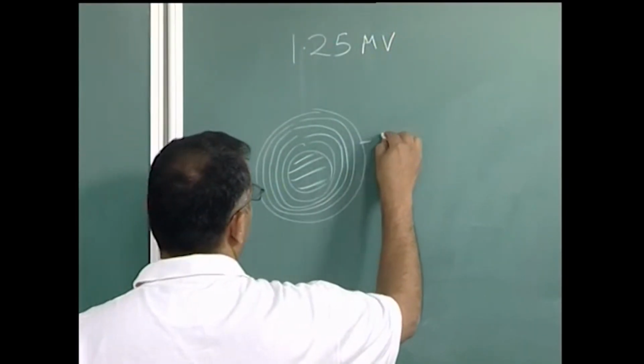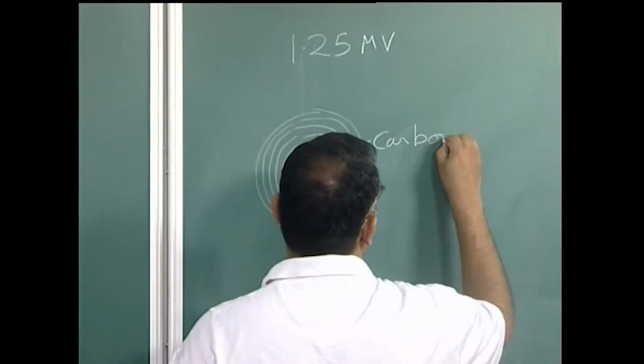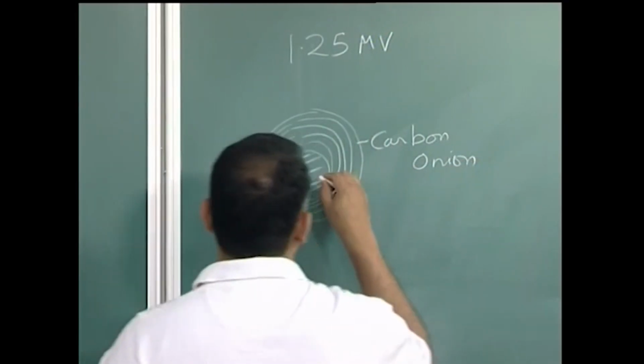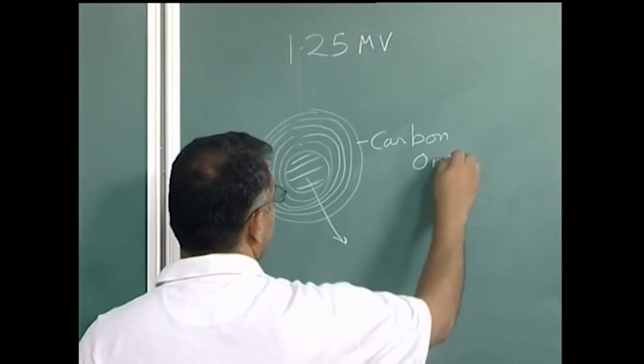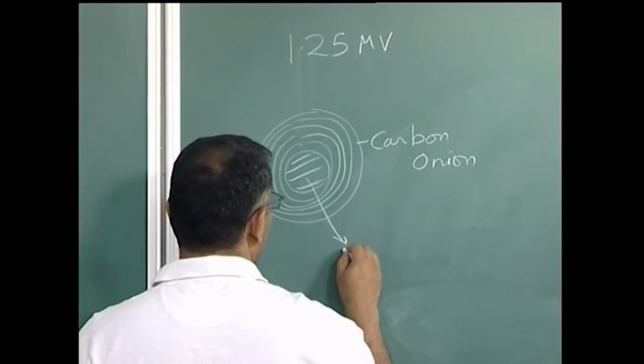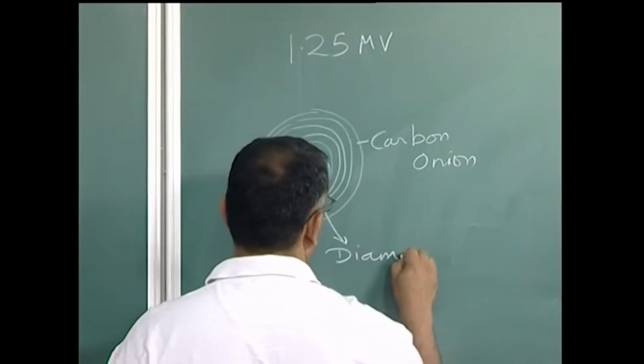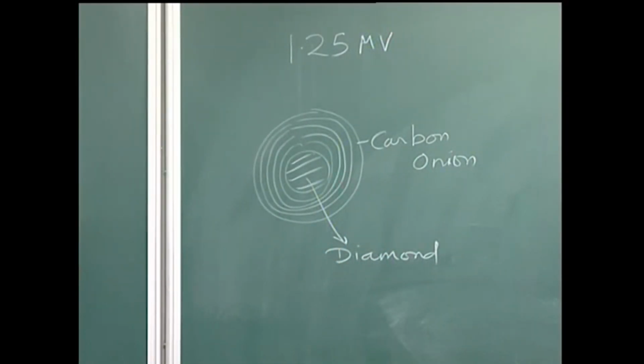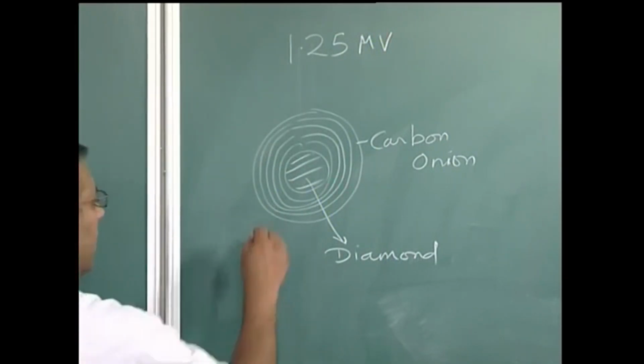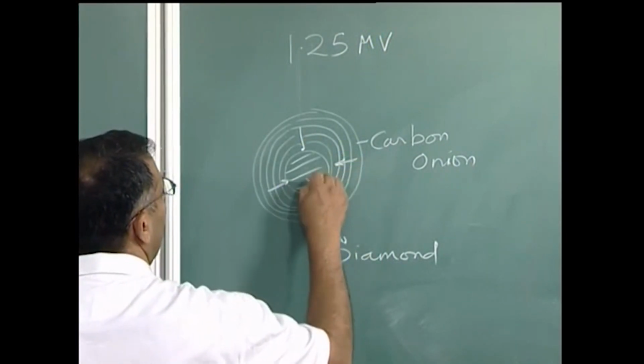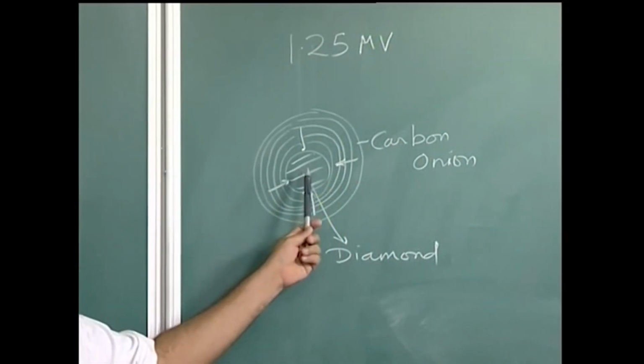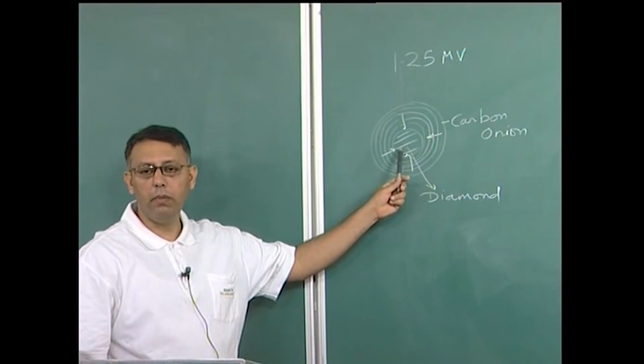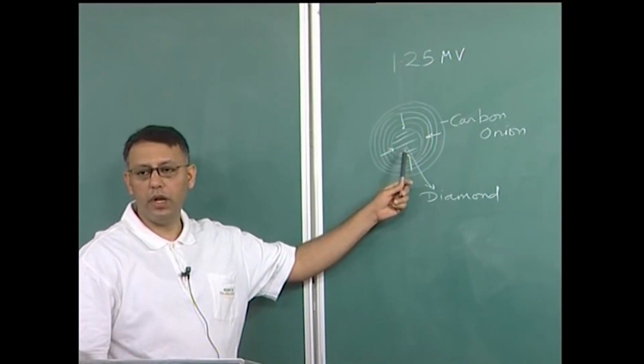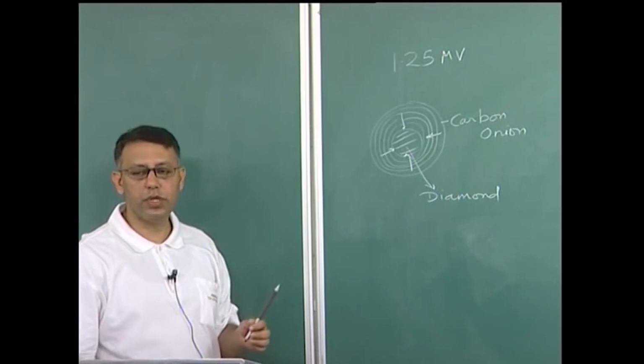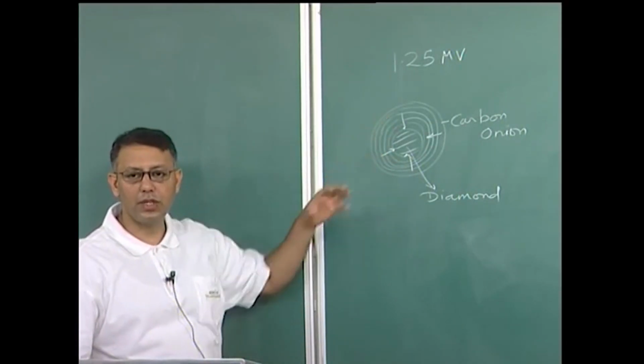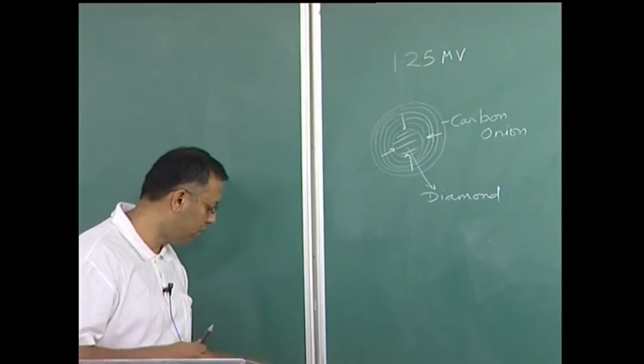So, inside these are the carbon onion, and this is, or more precisely, this carbon onion here, and this became diamond. In other words, under the electron irradiation and the intense pressure coming from these carbon shells, this interior of this carbon onion became diamond. So, this is a very interesting experiment which was published in Nature. So, you see that these carbon shells actually impose very high kind of compressive stress on the material inside.